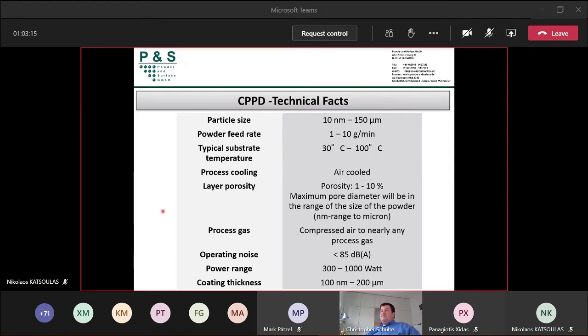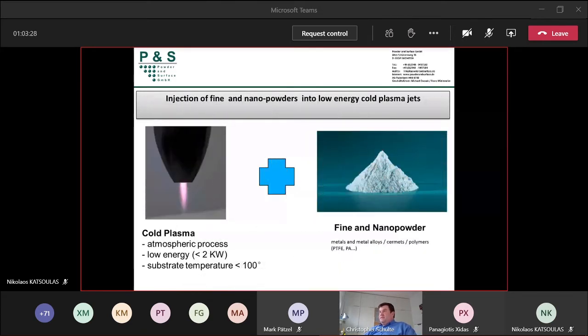And another point, the last point, is that we reach a coating thickness between 100 nanometers and 200 microns. It depends on what we want to reach. Okay, so please the next. So, yeah, a short summary. We have fine powder and we have a cold plasma jet. And together, we inject micro and nanoscale powders into a plasma flame, shoot these onto substrates and implant these into the polymer. That's the whole story.